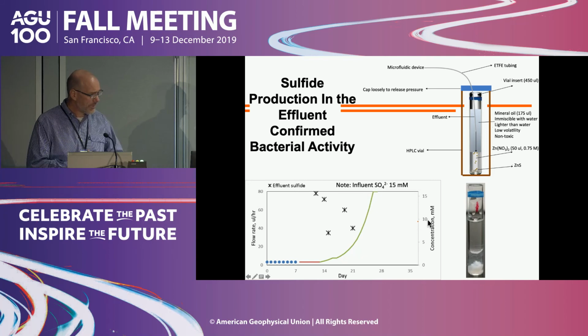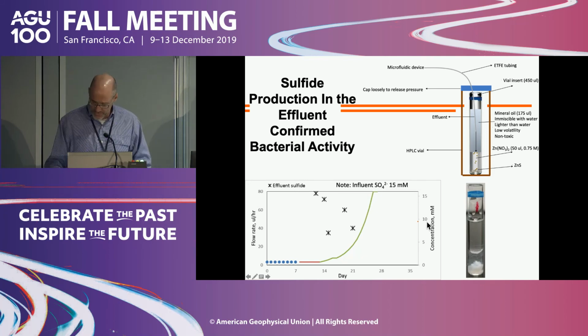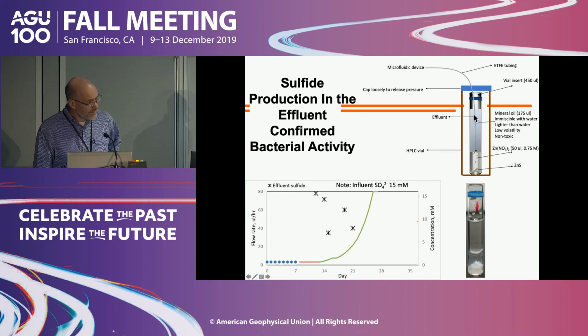We also captured the effluent and measured sulfide, and this was an idea of Long and another graduate student. Basically they have mineral oil here. When you get sulfate reduction, you get sulfide, and sulfide, of course, is easy to oxidize. So it would go into the mineral oil, which was a barrier to oxygen, and then it would drop down, and we had zinc nitrate. The zinc would react with the sulfide, and we get precipitates of zinc sulfide. And so we can measure the sulfide in the effluent that way.